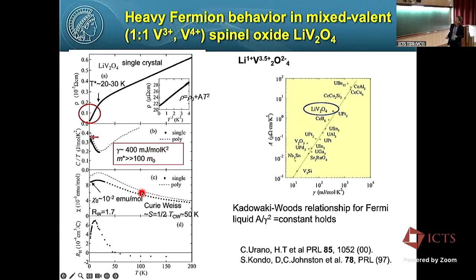Now look at the susceptibility. At high temperature you see Curie-Weiss behavior with a spin moment close to spin 1/2, and at low temperature the susceptibility is almost constant. With this T equals 0 susceptibility and the gamma, we estimate a Wilson ratio of 1.7. So it's clear it is a correlated paramagnet close to ferromagnetic. Okay? And below 20, 30K, we do see a large temperature dependence of the Hall effect like this, which I will discuss later.